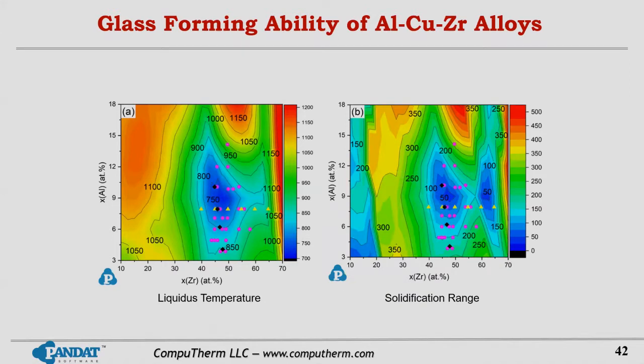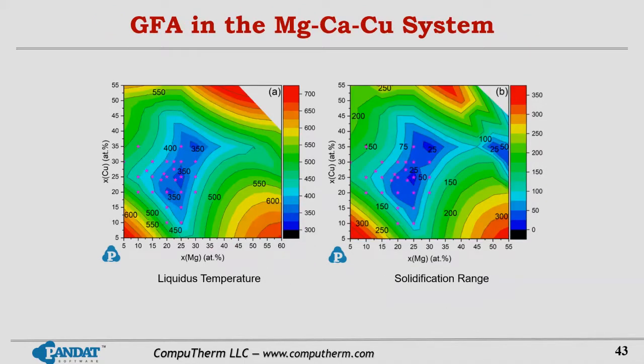We can also plot another color map of the solidification range, which also seems to be a good indicator for BMG formation. We performed simulations for some other ternary and higher order systems, and it seems high throughput calculation gives a really good indicator for searching bulk metallic glass compositions.